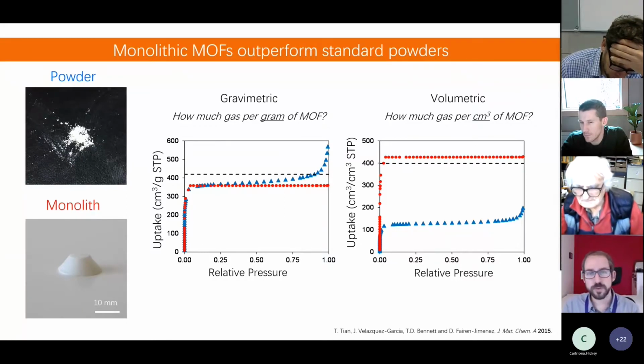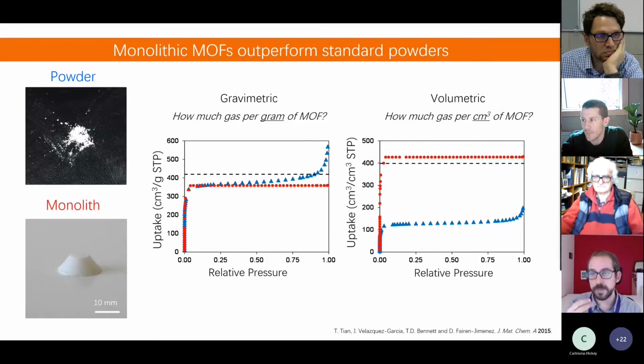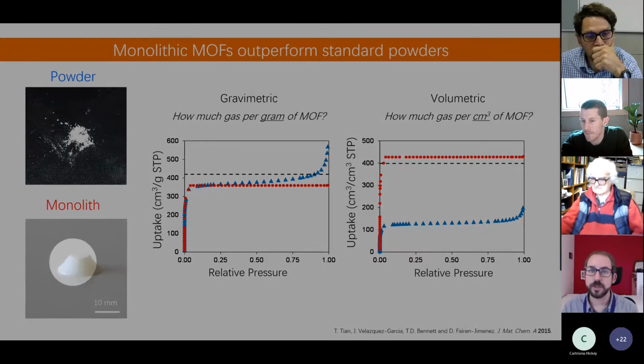So is the surface area important? Yes, it is very important, but also the density. And this is the big difference. Most of the time in the literature, you see people calculating volumetric capacities or volumetric surface areas by multiplying by the theoretical density of the powders. This is the single crystal density of the materials, what you can get from crystallography. But this is not correct, because obviously the powder has a lot of interstitial space between the particles, and even if you have a pellet, you will have a lot of macro porosity, a lot of dead volume that you cannot really exploit. The opportunity with the monolithic material is to be able to develop not only microporosity, but also to densify all the particles so we don't have any dead space between the material.